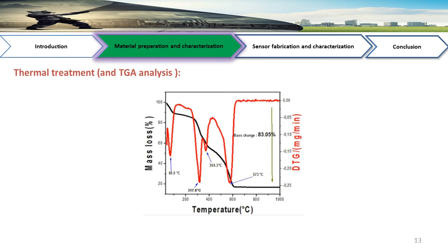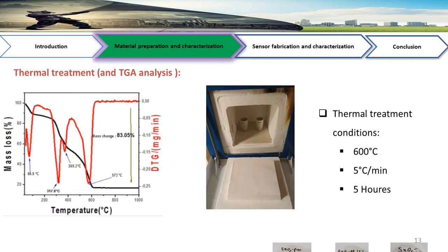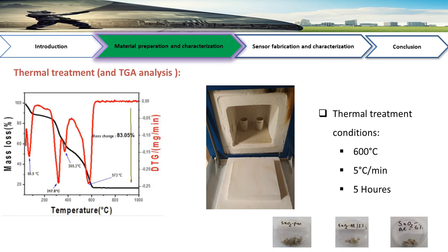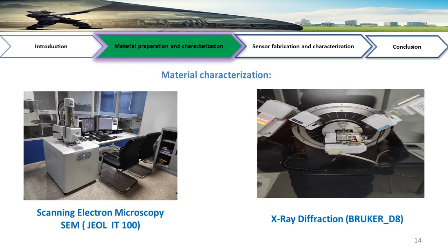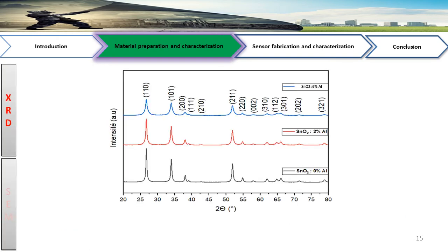In order to select the adequate annealing temperature to remove PVP and solvent, TGA analyses were performed. We can see in this graph that the temperature at which these elements are removed is 600 degrees. So the fibers were annealed at 600 degrees with a heating rate of 5 degrees per minute for 5 hours. The characterization techniques used are X-ray diffraction and scanning electron microscopy. X-ray diffraction analysis shows that the structure of our samples is tetragonal rutile, characteristic of tin oxide.